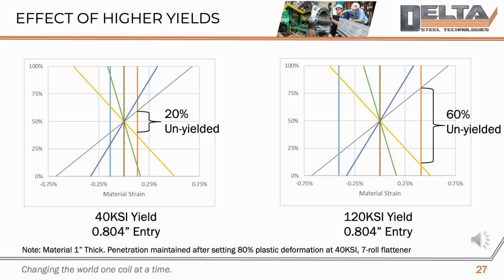The strain is higher, and the material behaves differently under the same leveling conditions compared to the 40 KSI material. Despite using the same number of rolls and the same penetration settings, the higher yield steel resists deformation more, so it requires more force to reach the target. This comparison highlights the importance of adjusting the leveling process based on the material's yield strength. Stronger materials need more precise control and more powerful equipment to ensure we achieve the desired flatness without overworking the material.